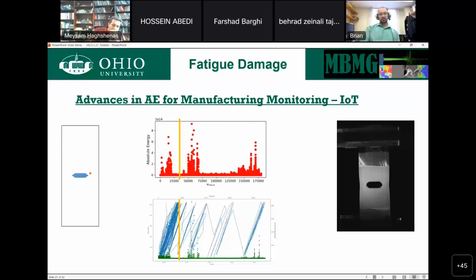And you can see that in the hysteresis loop, and I will apologize, these loops are very sparse. We only took 10 data points per cycle from the DIC, and we only did that every 100 cycles in order to account for the 7,000 cycles we're doing and not having too much data to process. But you can see in the hysteresis loop that we have little happening. We see it starts to deviate some as the crack is growing, and as the crack grows larger and larger, it starts to deviate faster and faster. The AE is reflecting the same thing.